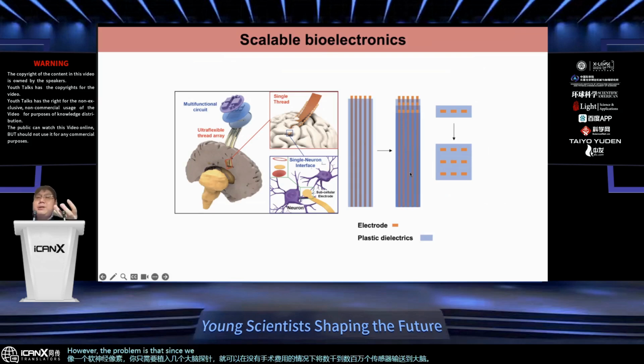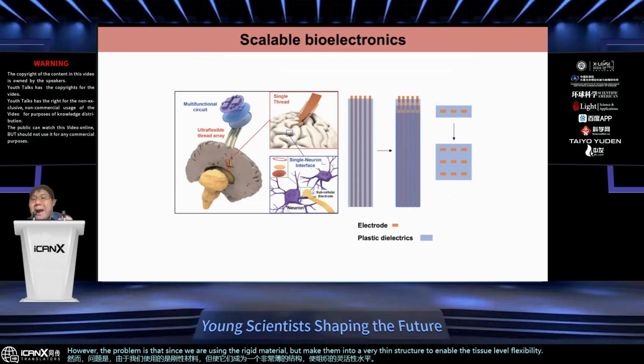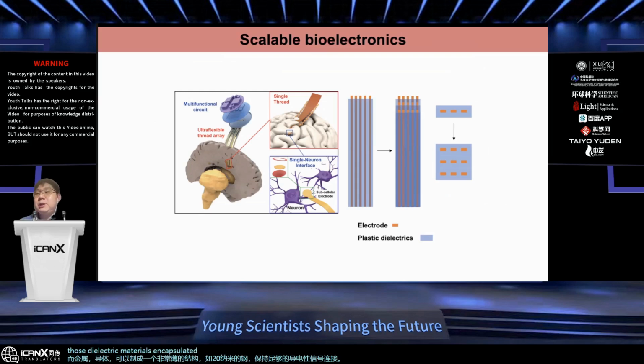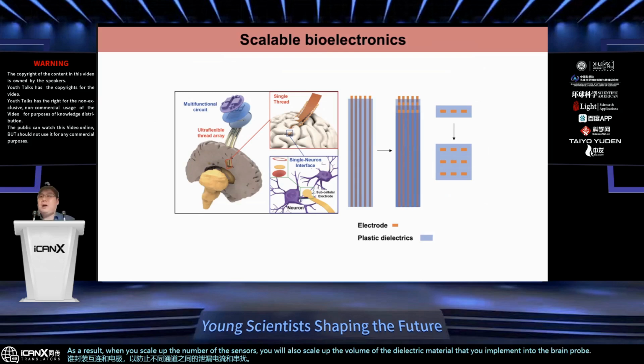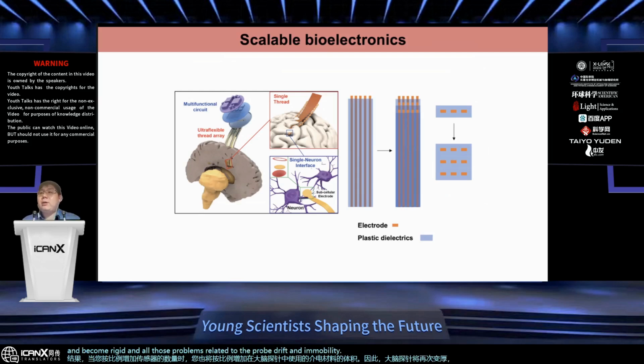However, the problem is that we are using rigid material but making it into a very thin structure to enable tissue-level flexibility. While the metal conductors can be made into a very thin structure, like 20 nanometers, and still maintain enough conductivity for signal collection, the dielectric encapsulation material cannot be further reduced, because it needs to maintain a certain thickness to encapsulate the interconnects and electrodes and prevent leakage current and crosstalk between different channels. As a result, when you scale up the number of sensors, you also scale up the volume of dielectric material in the brain probe, so the probe becomes thicker again and rigid, and all those problems related to probe drift and immune response come back.